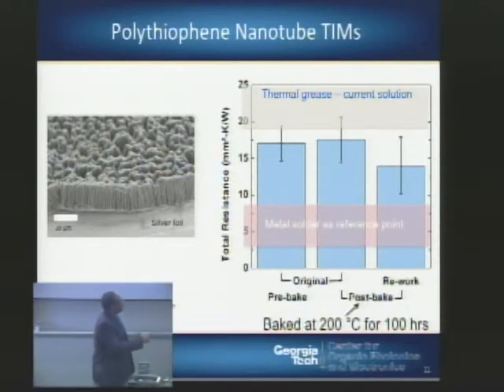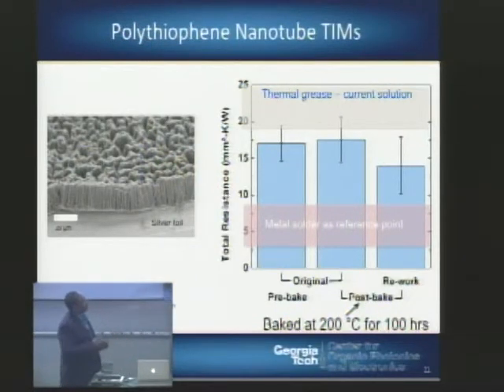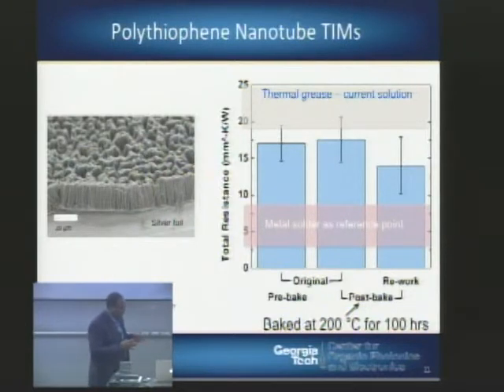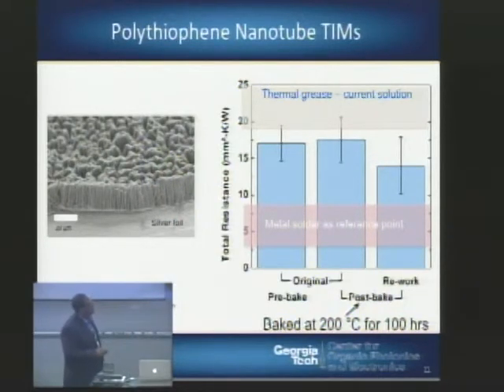But here we go. So here are the polymer nanotubes, and here's the interesting thing. If we look at the current technology in terms of thermal greases, the total thermal resistance for that particular interface is somewhere between about 18 to 25 millimeter squared K per watt. And you can see where these polymer nanotubes are actually performing. They're outperforming the commercial thermal greases that are used in these applications.